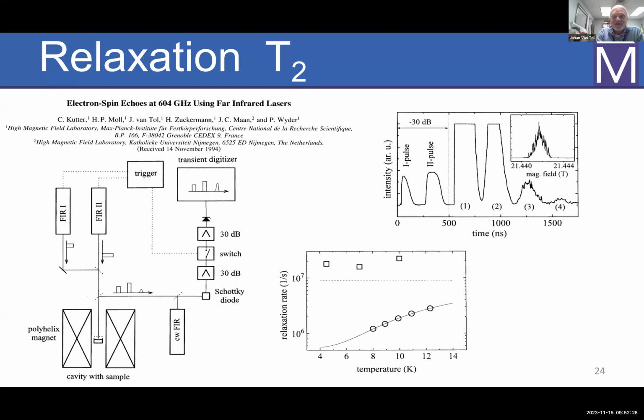But one of the things that surprised us was that if you looked at the T2 in these systems, it was longer at 600 gigahertz than it was at X-band for these concentrated systems. So we scratched our heads a little bit, but then we hypothesized that the 1 over T2, if you think that the T2 is determined by the fluctuations of your surrounding electron spins, that these fluctuations slow down if your spin system starts to get polarized. So if your spins are all pointing up, there are no pairs of spins that can fluctuate. So your relaxation rate actually goes down.